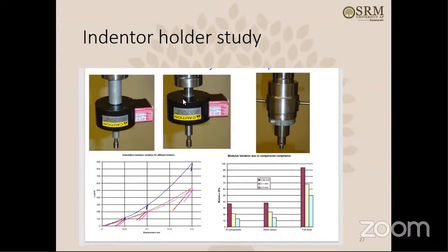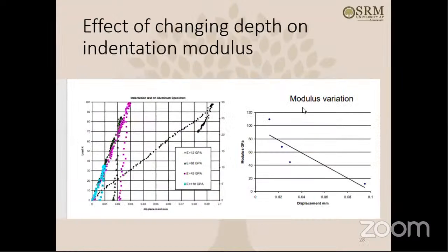Instead of that, here a steel sleeve is used, and here the complete setup is different, as you can see. Different kinds of setups are used, and we saw that it is affecting these loading unloading curves, as you can see, and that's why it is affecting the modulus level. So this shows that the load frame compliance has a big effect on this testing setup. Also, the effect of changing depth on the indentation modulus. If you do the testing with different depths, then of course it also shows modulus variation.